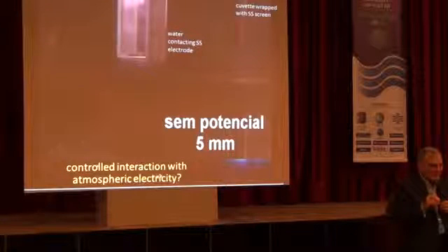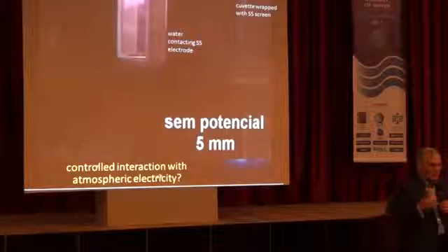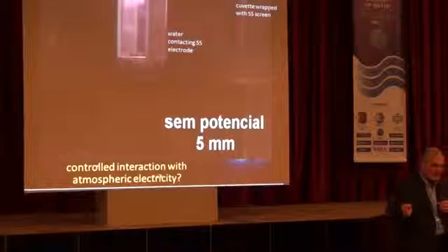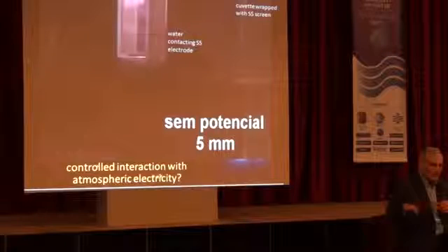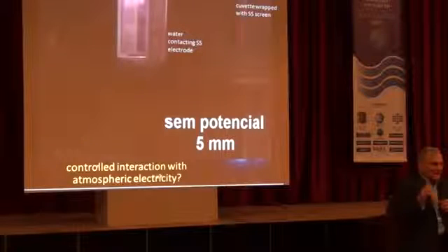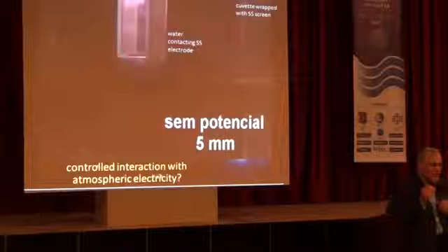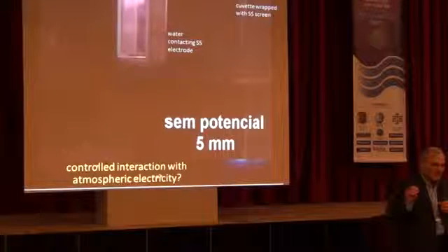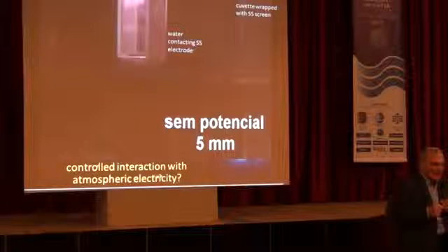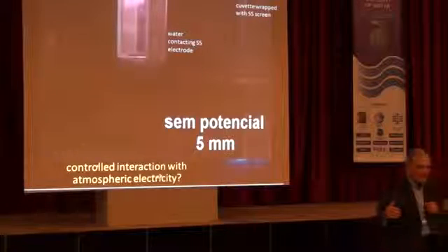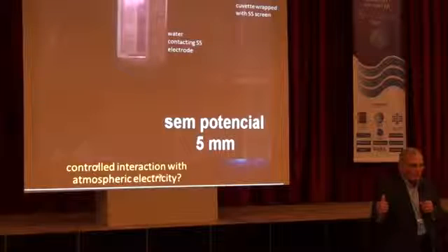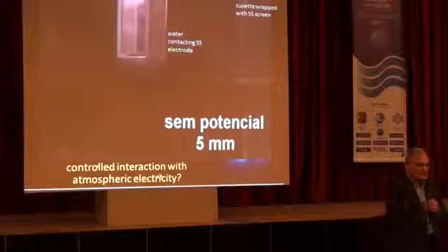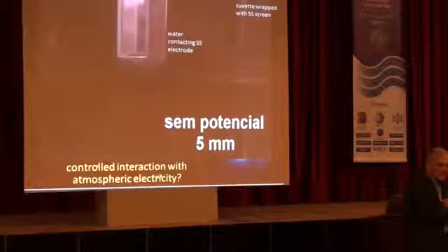So, to conclude, electrostatic charges are really more dangerous under low humidity than at high humidity because they last for longer. And what we should not do to build electrostatic charges: we should not expose an item to very high humidity and quickly transfer it to very low humidity.